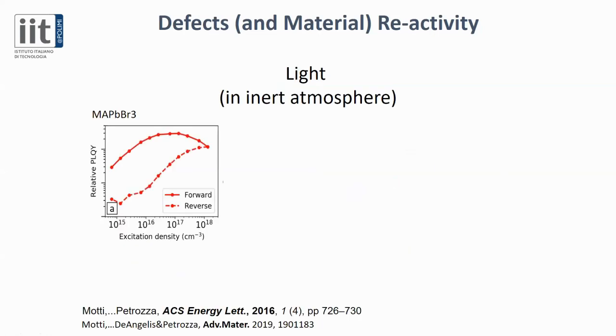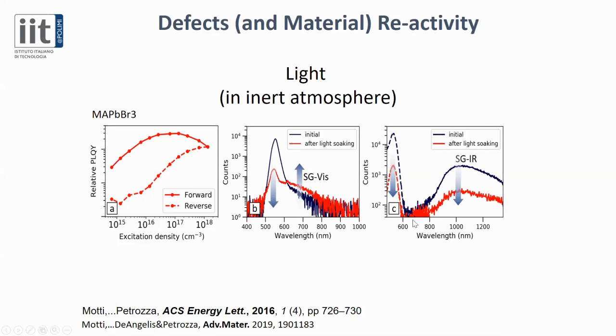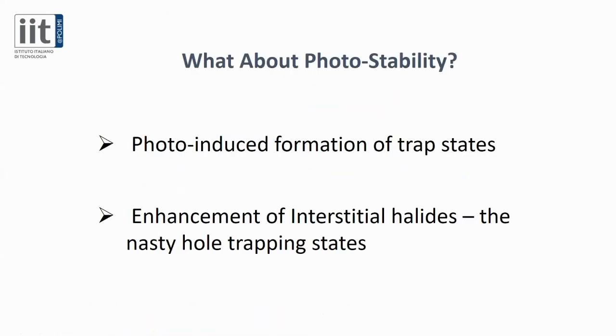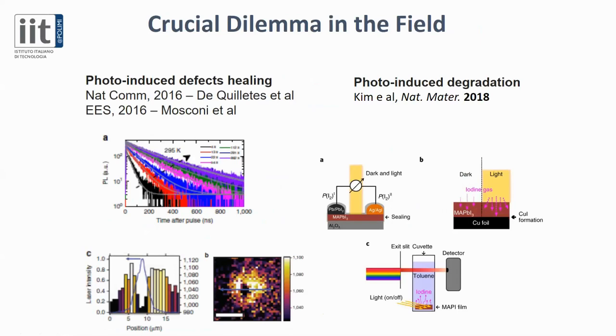Now, what happens under light? What we found is that when we excite a metal halide semiconductor, so under light, we are actually inducing the formation of defects. You see here the relative PL quantum yield when we increase the excitation density, and then when we go back, and you see there is a sort of hysteresis, which is mainly due to the formation of defect states. And as you can see here, we are definitely increasing the density of hole trapping states. So this was a sort of dilemma in our group, and also in the field, because there were two very different observations by different groups. Few of us were observing a photo-induced defect healing.